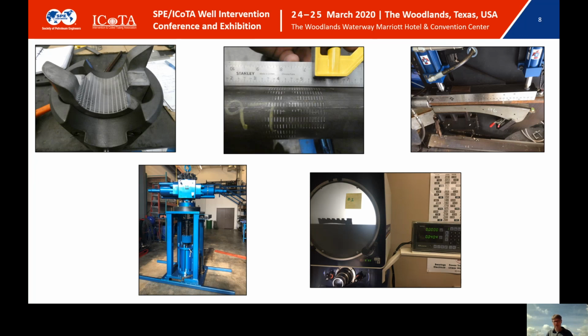The top right photo is of the bend fatigue machine that was used. This is one of the Steve Tipton style bend fatigue machines. The bottom left is a picture of our single BOP with the pipe slips in it, and the pipe, and the bottom part is the ram that we used to pull tension into the pipe. And the bottom right photo is an imprint using metrology putty of the slip damage being examined on an optical comparator, which is what we use to measure the mechanical damage to the slips.